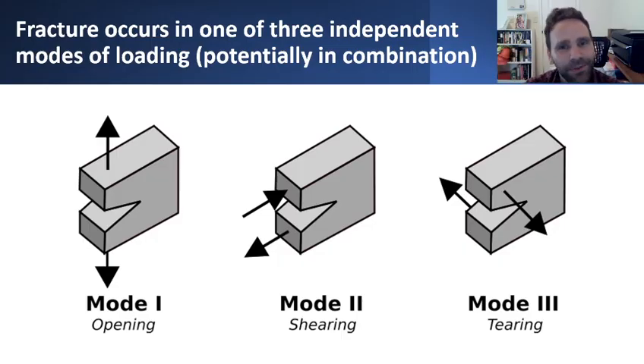And then there's mode three, which is tearing. It's kind of like the mode of fracture that would occur if you took a piece of paper and you literally tried to tear it in half like that. So subjecting the specimen, in this case, let's say, to anti-plane shearing deformations, which is kind of like you're loading now this thin piece of material, not due to in-plane loading conditions, but due to out-of-plane or transverse loading conditions.